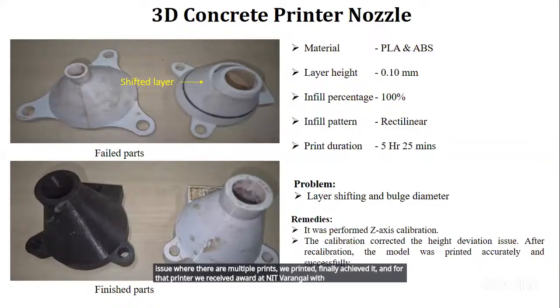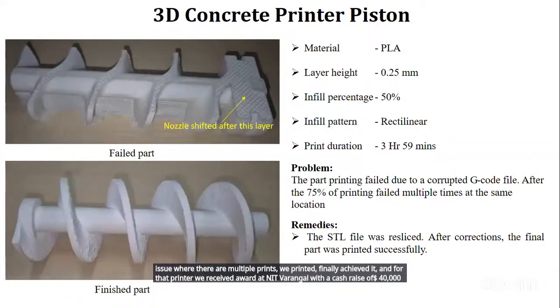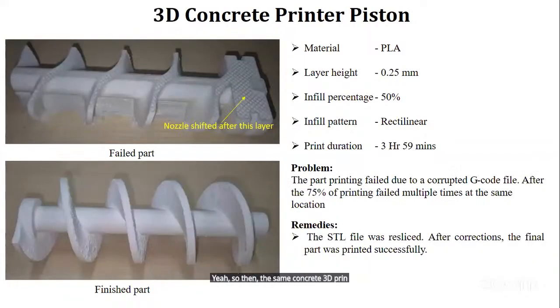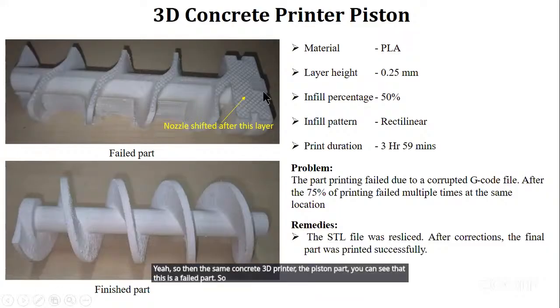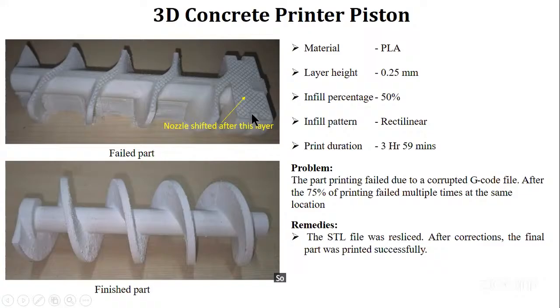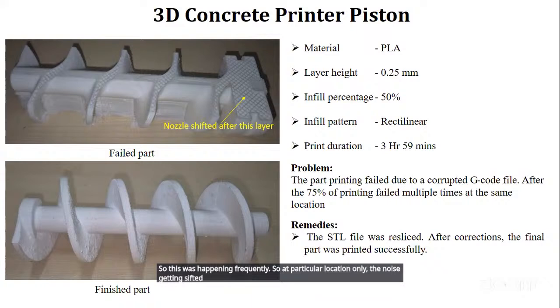prize of 40,000. Yeah. So then, the same concrete 3D printer, the piston part. You can see that this is the failed part. We had almost finished around 70% of the part, and the nozzle shifted after this layer. So this was happening frequently. At a particular location only, the nozzle was getting shifted when we were printing this component. We tried multiple times and the same error came, and we were wondering what was happening.